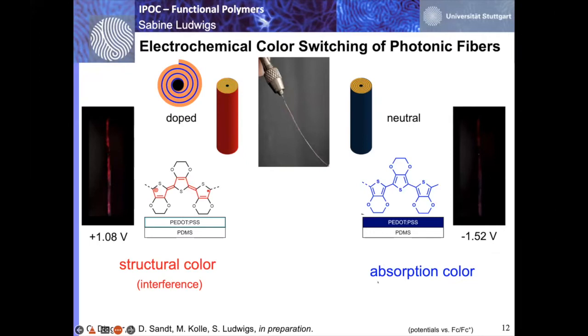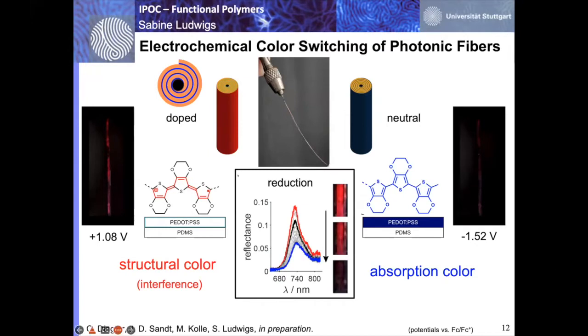This is what we attribute to the absorption color of the neutral state, whereas the state at plus 1.08 volt is attributed to a so-called structural color because of this particular build-up of the fiber, this multi-layer cladding. So there are interference effects in play, essentially. Here you see it nicer in the picture. The reflectance is really changing here from red, going down in this direction. And also here you can reversibly change this reflectance in an electrochemical experiment. So that's one nice property using this electrochromism and going towards structural colors, where you can change the structural colors also by changing the film thickness.